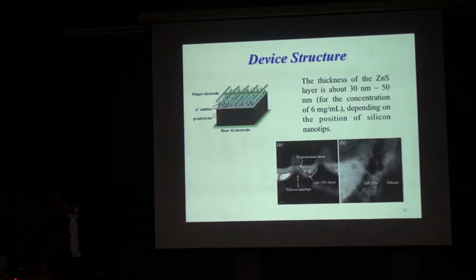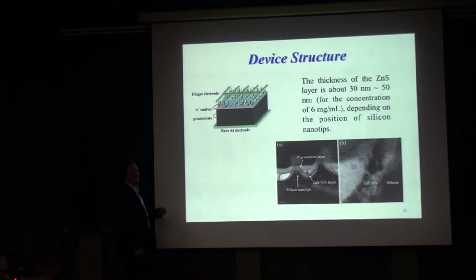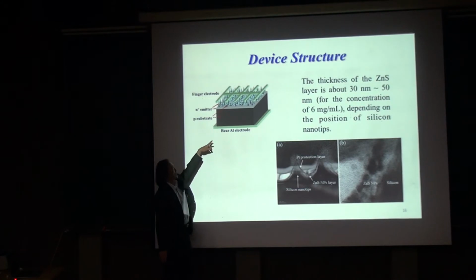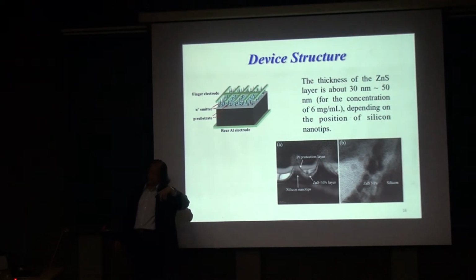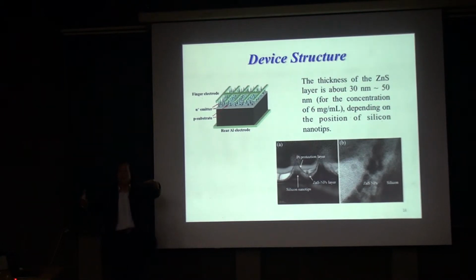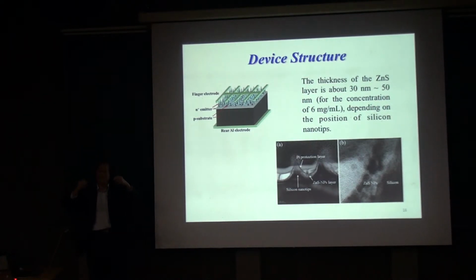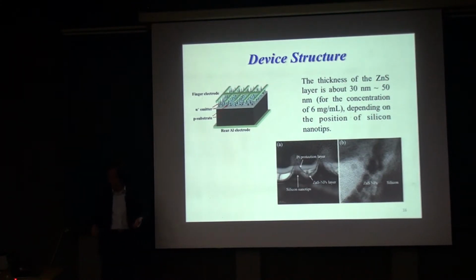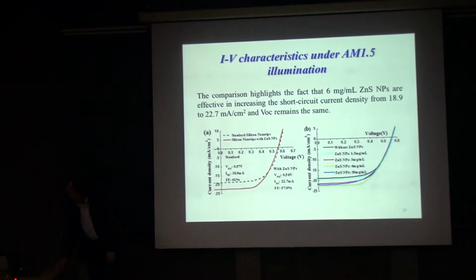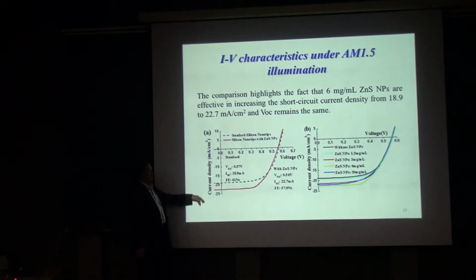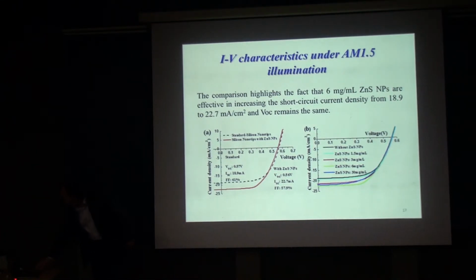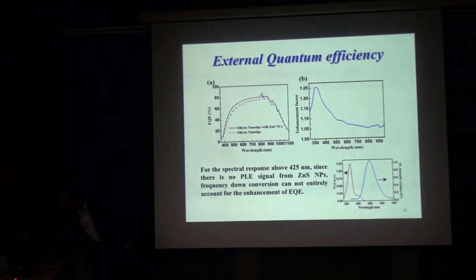Okay, this is a diagram to show our device structure. We fabricated the silicon nanotips, and on top of that, we deposited the semiconductor quantum dots to see if we can enhance the solar cell efficiency. And this is our result. The black one is without quantum dots. The red one is the device with quantum dots. And then you can see the efficiency can be enhanced by more than 10%.